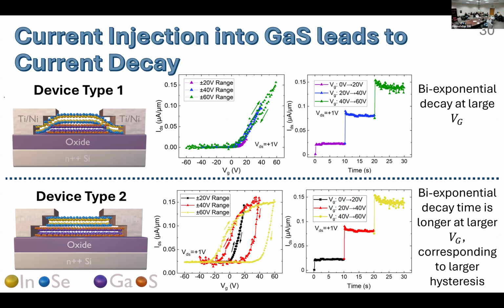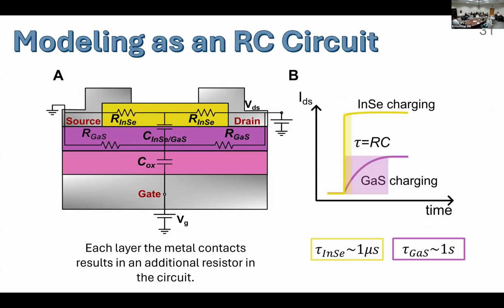In device type 1, we look at the transfer curves and the time conductance measurements as we change the gate voltage from 0 to 20, 20 to 40 volts, 40 volts to 60. And we see that there is a significant bi-exponential decay in the current for the devices in the device type 1 configuration, in the order of a couple seconds. So if you recall from maybe physics 2, when we were introduced to RC circuits, we can actually model this as an RC circuit in which each layer that the metal contact is touching results in an additional resistor in the circuit.